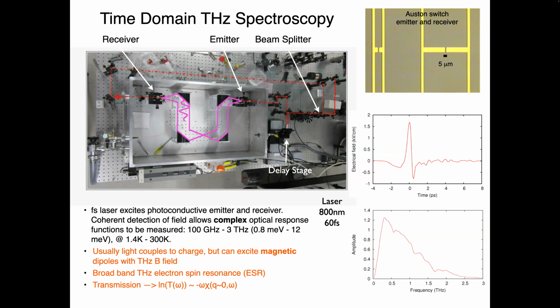The most straightforward things you can do, I'll show some examples, is where you're measuring the charge response of a system. Right? So if it's a metal, or you have phonons at low frequencies, something like this. If it's a material which is, let's say, electrically uninteresting, it's an insulator at low frequencies, but it has interesting magnetic degrees of freedom, then the time-varying magnetic field of the terahertz pulse, you have time-varying electric fields and magnetic fields, can couple to, say, the magnetic dipole excitations, and it provides a very precise way of doing magnetic susceptibility experiments as a function of frequency, giving information which is very complementary to neutron scattering.